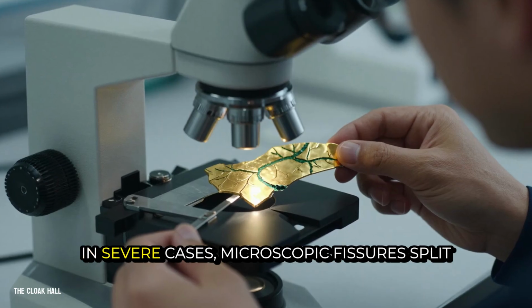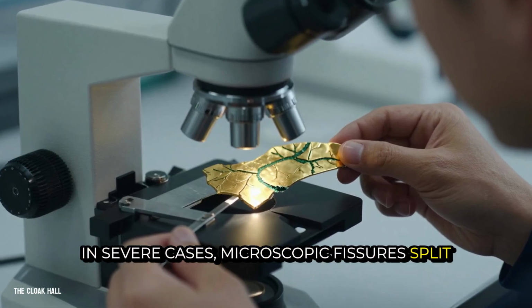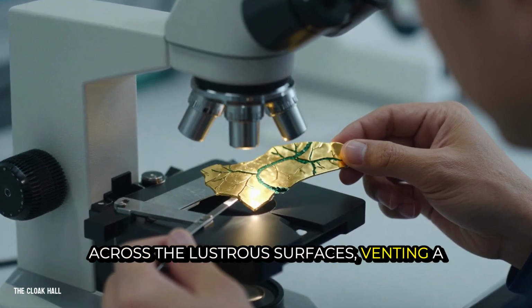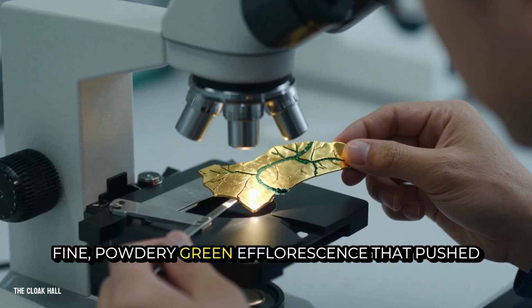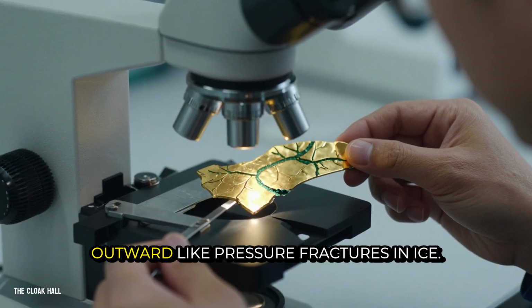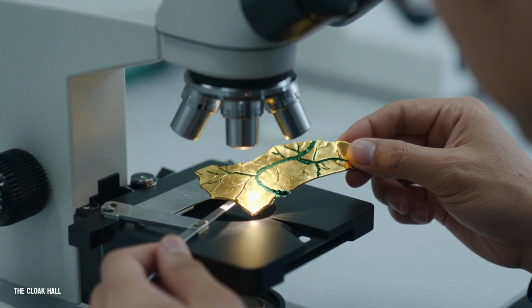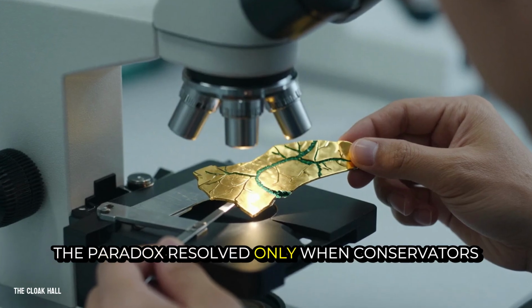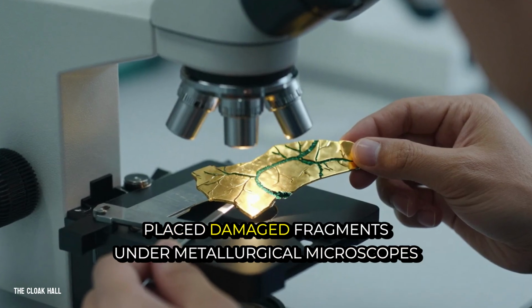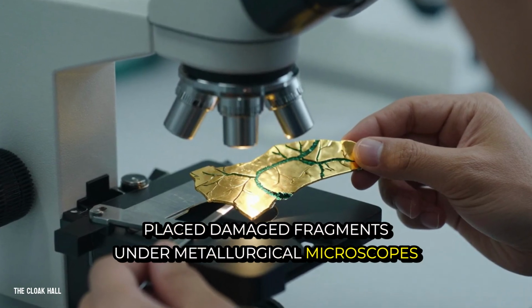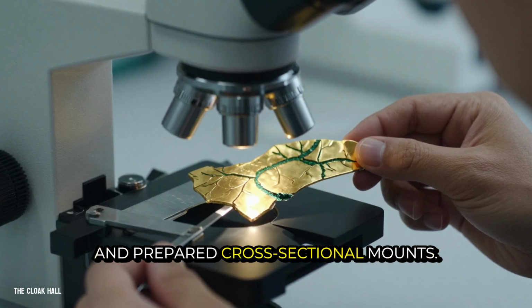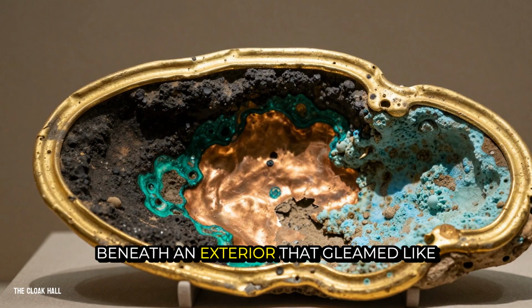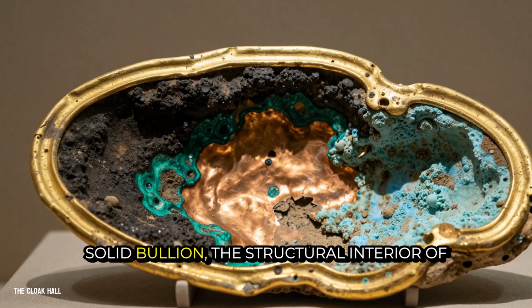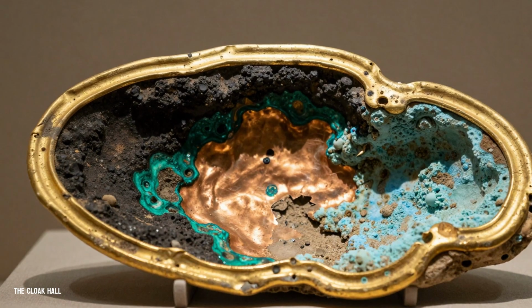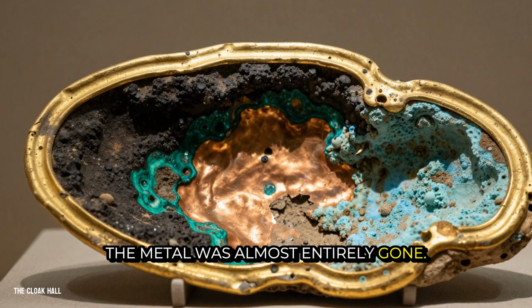In severe cases, microscopic fissures split across the lustrous surfaces, venting a fine, powdery green efflorescence that pushed outward like pressure fractures in ice. The paradox resolved only when conservators placed damaged fragments under metallurgical microscopes and prepared cross-sectional mounts. Beneath an exterior that gleamed like solid bullion, the structural interior of the metal was almost entirely gone.